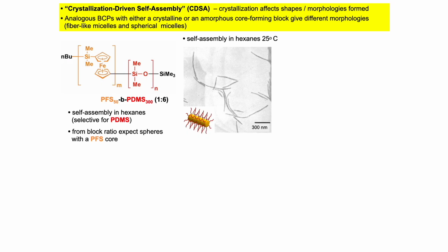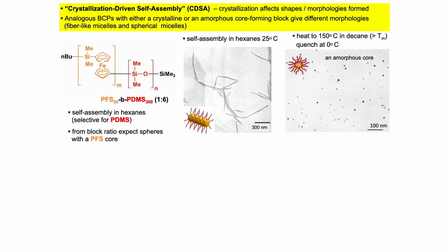So why do you get these fiber-like structures? Well, if you assemble this block copolymer, instead of at room temperature, you do it at 150 degrees. That's above the melting point for this block. And so at 150 degrees, if you do the self-assembly, this block doesn't crystallize because it's above the melting point. And remarkably, what you then get is the spherical micelles that we expected.